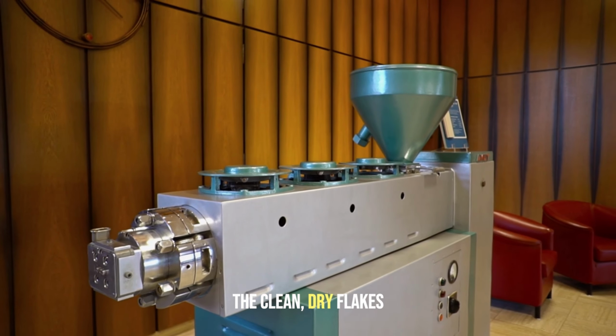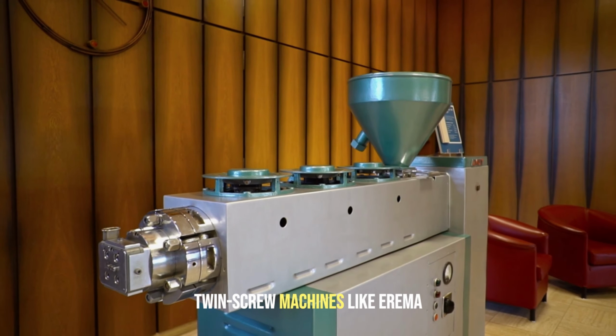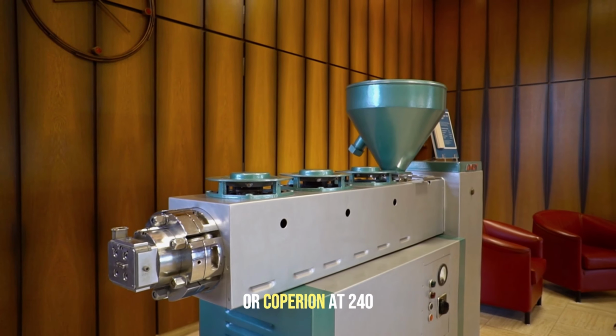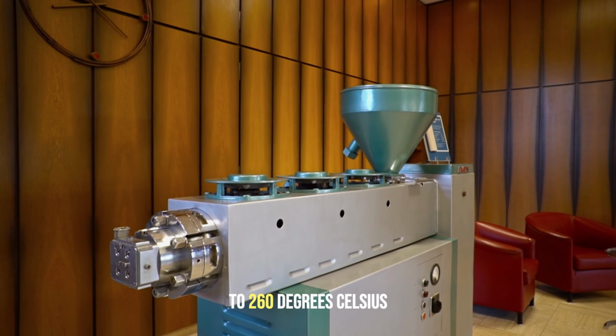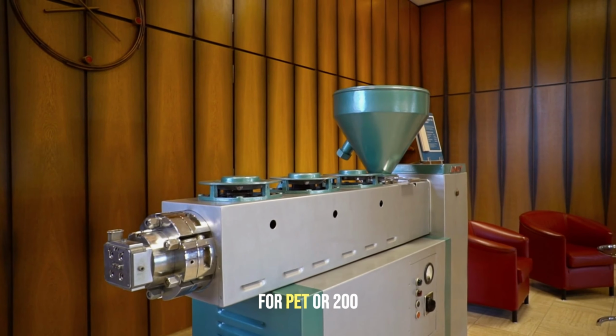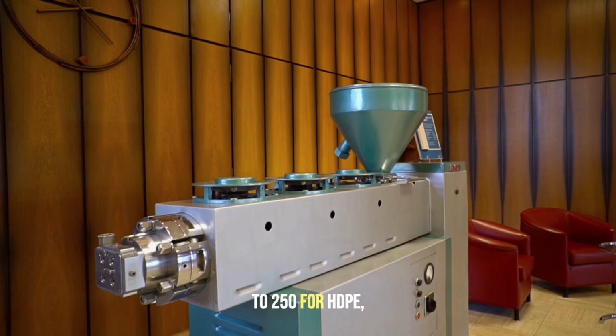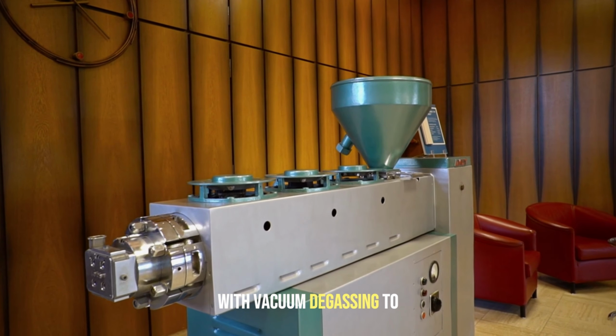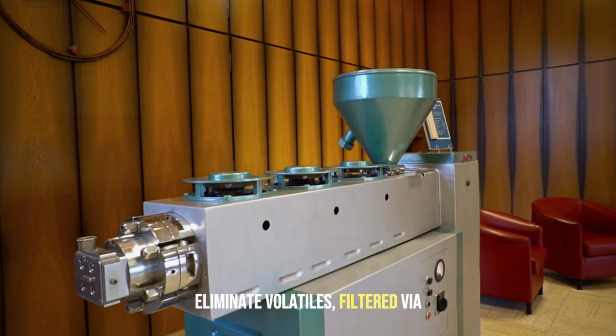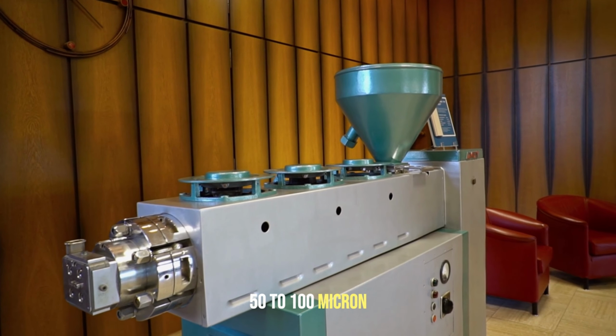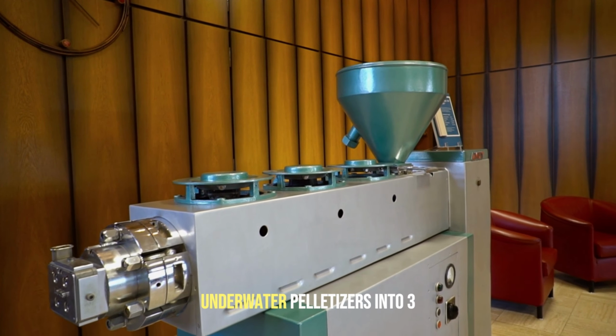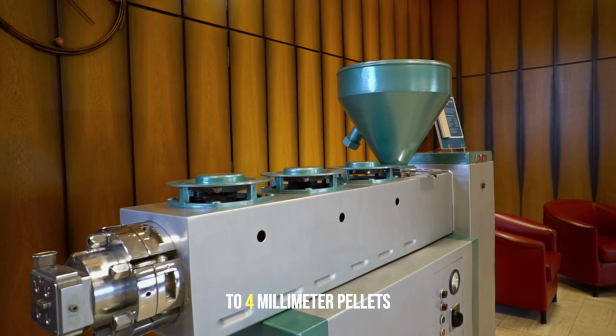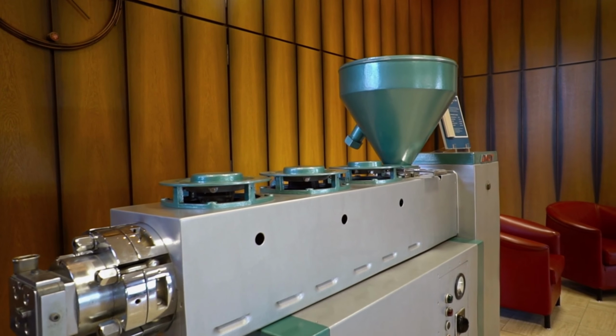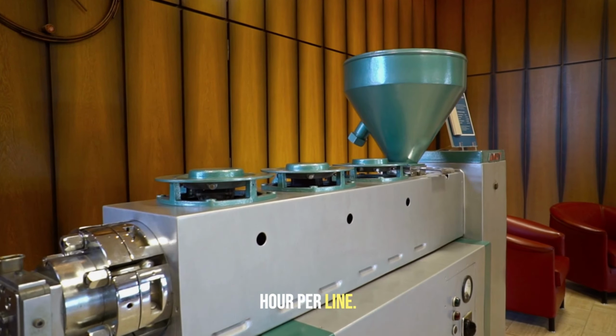The clean, dry flakes are then extruded in twin-screw machines like Erema or Coperion at 240 to 260 degrees Celsius for PET or 200 to 250 for HDPE, with vacuum degassing to eliminate volatiles. Filtered via 50 to 100 micron screens, and cut by underwater pelletizers into 3 to 4 millimeter pellets at rates of 100 to 300 kilograms per hour per line.